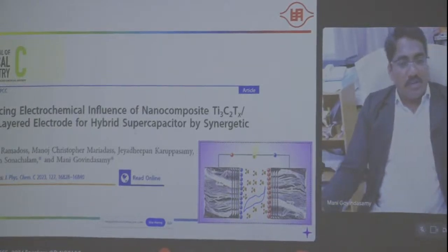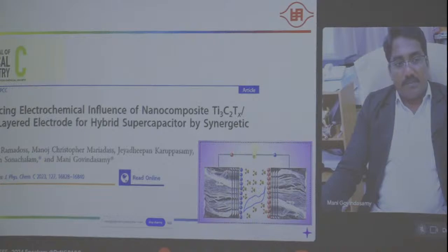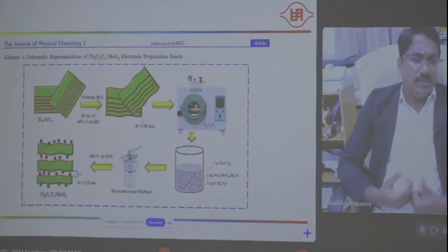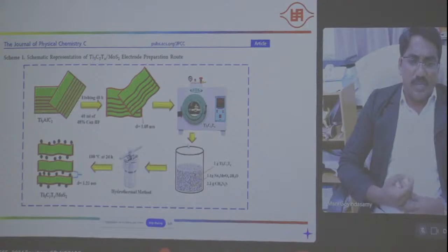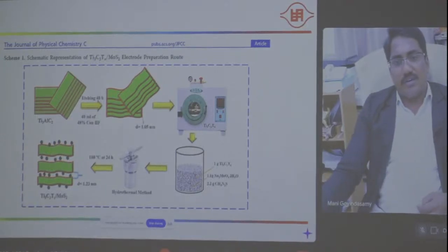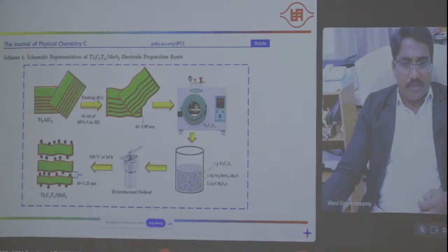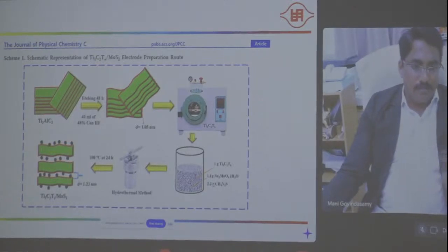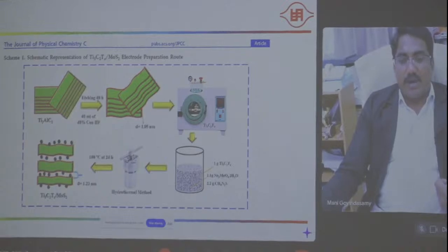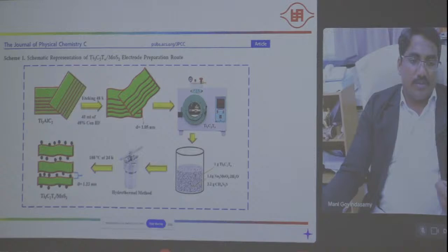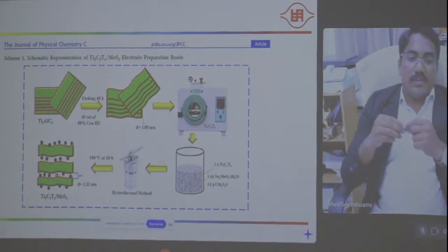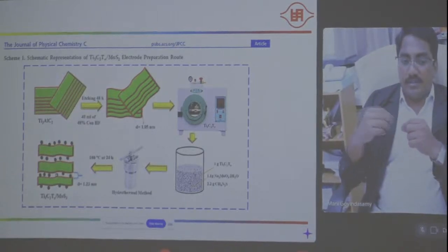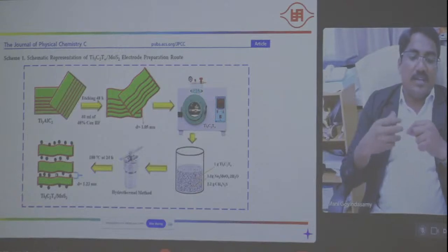For example, in this work we used MXene related molybdenum sulfide as a hybrid supercapacitor. The similar procedure: HF etching is the first step. The second step, we used the hydrothermal technique to combine with metal sulfide. We use the molybdenum precursors and the sulfur sources, then go for the hydrothermal technique. Finally, we get the MXene combined with molybdenum sulfide, like a multi-layer